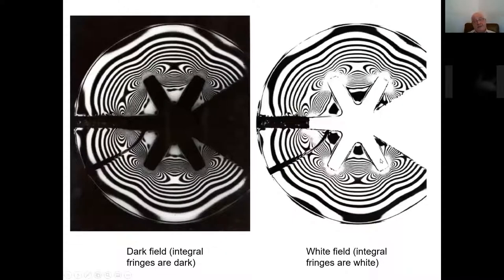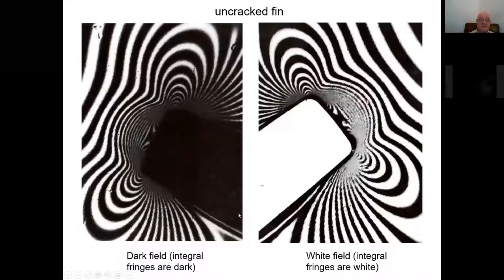And here you have some fringes in one of the models. On the right side, here was the crack. This part was taken out. This is a slice cut from the model just for demonstration purposes, to see essentially what happens around the surface of the fin, in dark field and in white field. And of course, the problem is that you have many fringes. And these many fringes, you can see them here.